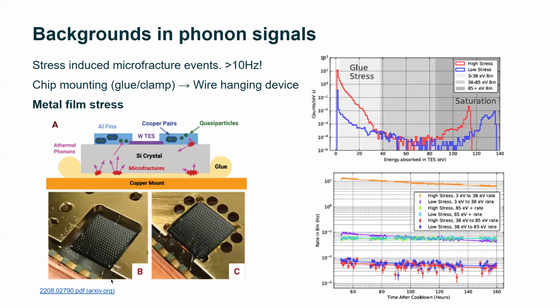What we figured out, this is a nice paper put out by a student in our group: if we glue the chip down onto the copper holder, because of thermal contraction, after we cool down, there are microfractures releasing small amounts of energy randomly. So you see a huge amount of events. This is the red curve, compared to the device on the left, which is hanging there freely by aluminum wire bonds. So this is minimum stress, red versus blue. You see a huge amount of events introduced simply because of the thermal contraction and the stress. We know this is not dark matter because we saw this event rate go down exponentially over time. This time dependence tells us this is not dark matter, but some kind of background.